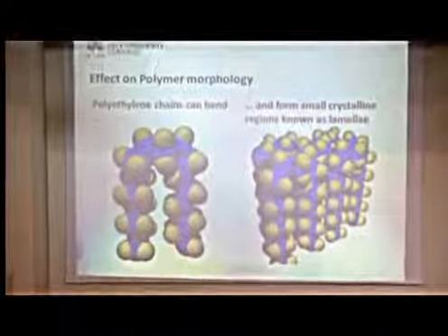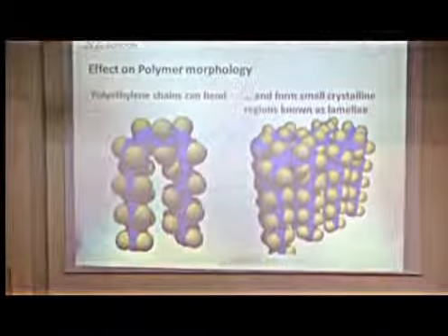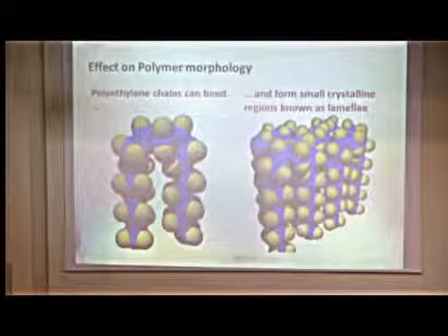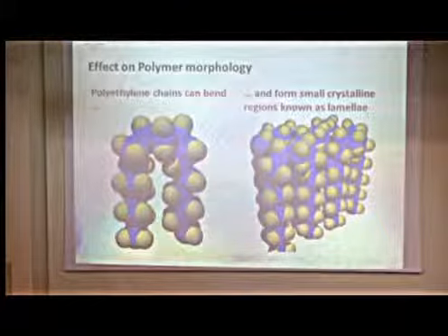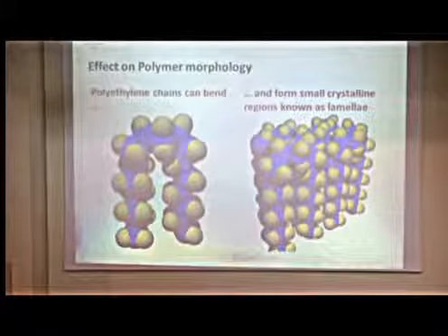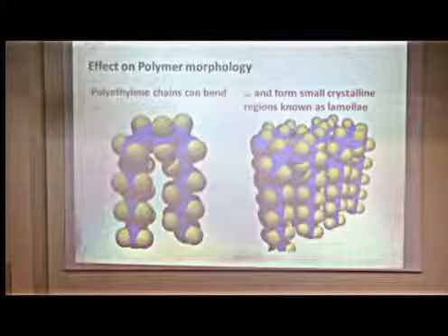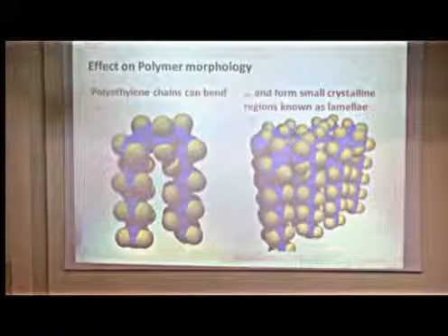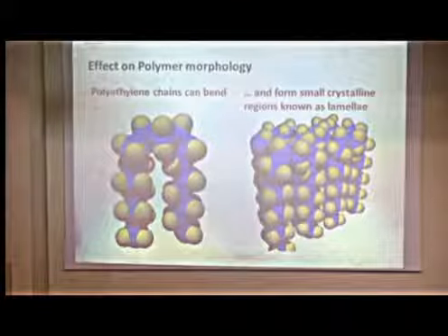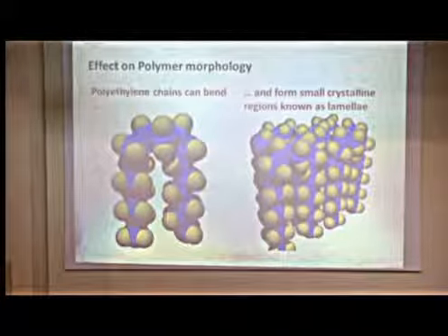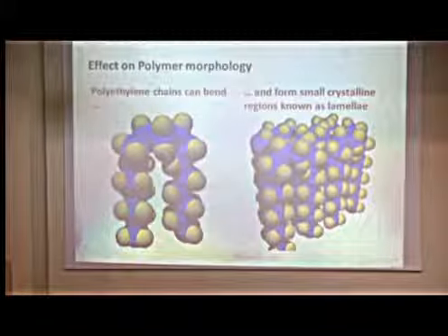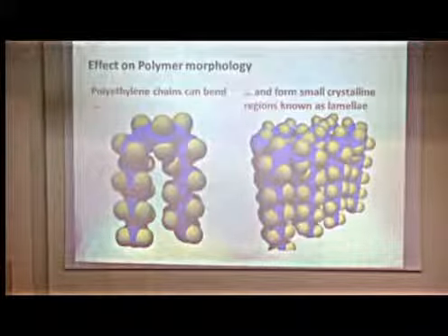And so these are likely to be relatively thin sheets, I suppose, up to a few tens of nanometers thick, perhaps a little bit more. They could be quite wide, a micron or several microns wide in their other dimension. And one could argue, in fact, that polyethylene is itself a nanodielectric.